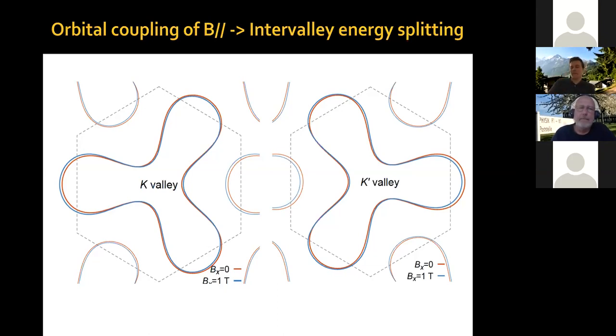So for example, for the normal state anisotropy that I've shown, the question is, is it really a nematic order or a smectic order? In the sense that, is it only lattice rotational symmetry that is broken, or do you also have translational symmetry broken, like, for example, stripes? The more generic feature that we can say is nematicity, but it could be smectic. Maybe we have charge density wave or a stripe order in that region of the normal state phase of the phase diagram. So we don't know that.